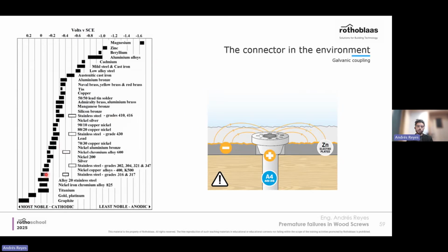Galvanic coupling happens, and is stronger, depending on the material. The further apart two materials are in this graph, the quicker the galvanic coupling will be. And in some cases, the galvanic coupling is so low that it can be deemed irrelevant. For example, we offer many solutions that use aluminum plates with zinc-plated screws. They are different materials, but the galvanic coupling is so low, the corrosion is very, very slow, that it's almost irrelevant. Within the context of the design service life, you can even not consider it.